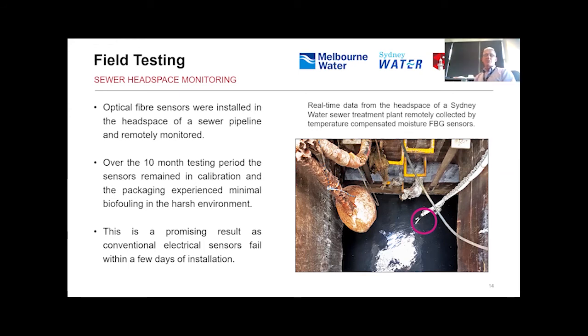The plan was to do it over 12 months, but some contractors turned up one day and actually trashed our sensors. But certainly in that 10-month period, they survived a number of flooding events. There were issues with nappies and baby wipes wrapping themselves around the sensor. But they performed as expected all the way through those nasty cycles.